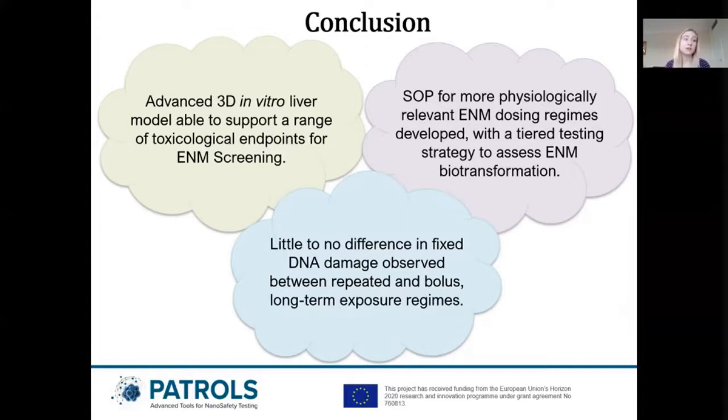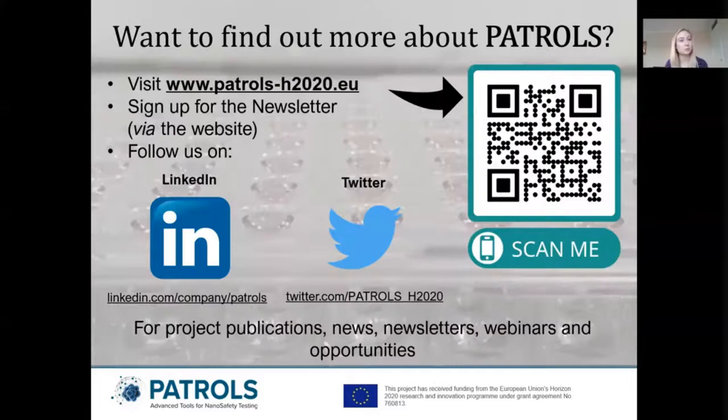In addition, we actually found that there was little to no difference in fixed DNA damage observed between repeated and bolus long-term exposure regimes. Now, we're currently doing a little bit further investigation with the pro-inflammatory markers and liver functionality, but at this stage there doesn't seem to be much difference between whether you do a bolus or a fractionated dosing regime. But yes, I'm sure more information on this will be published in due course.